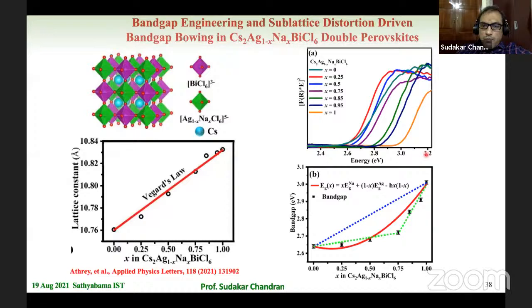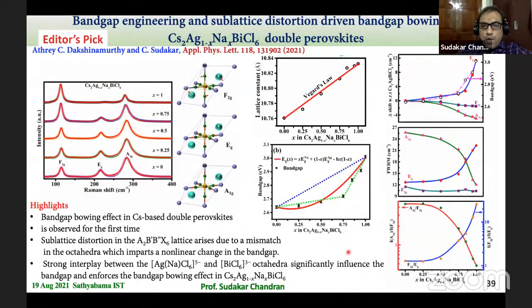But then when we measure the band gap of these materials, we found this does not vary in a linear fashion, and there is a nonlinear way we see. And you can fit this curve to some extent using a Bowing parameter. But then when we try to understand why such a deviation is seen, using Raman spectroscopy, we found a very simple, very interesting thing, that the sublattice distortion is the reason for such a deviation in the band gap. So what is sublattice distortion?